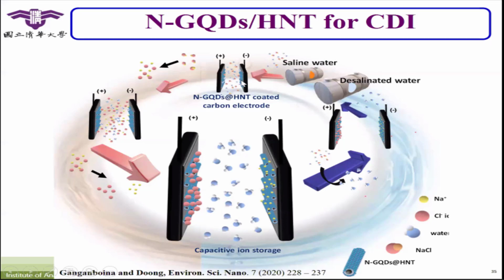to use for capacitive deionization. So we just apply some brown waters or gray waters to get inside. They contain some contaminants and ions. When they pass through the cells, all the ions will be removed. They absorb on the surface here, and only water molecules can penetrate. So after the treatment, you will see that the contaminated water that contains some impurity, the color is pink, and then becomes blue, meaning the color of pure water molecules here, and then we can get the desalinated water here. So the concept is very simple.